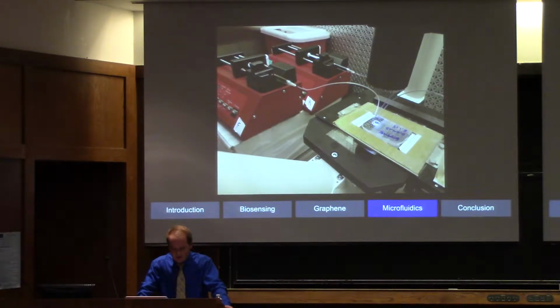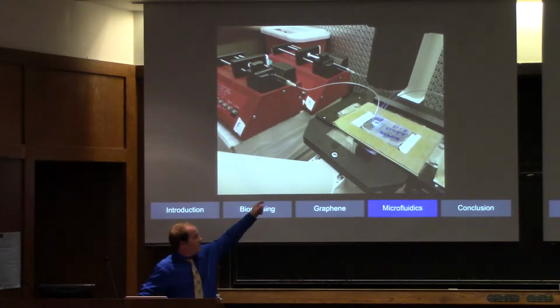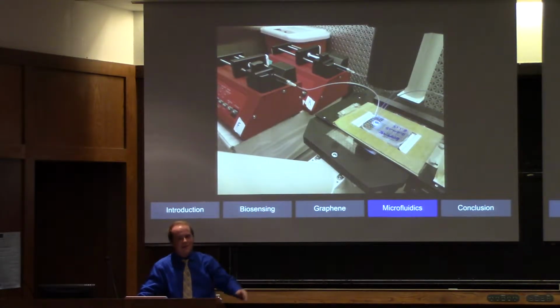You can also see here that the Nano lab uses the PDMS mold with the different wires sticking out of it, and they actually attach theirs to a glass slide using this plasma etching. But unfortunately for us, this plasma etching didn't work with our devices. We think it's probably a result of the large surface area covered by the graphene or the gold contact pads that's just sort of preventing the bond from actually forming.